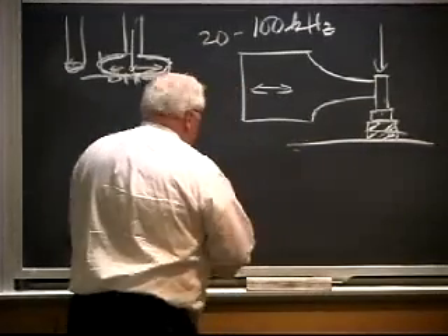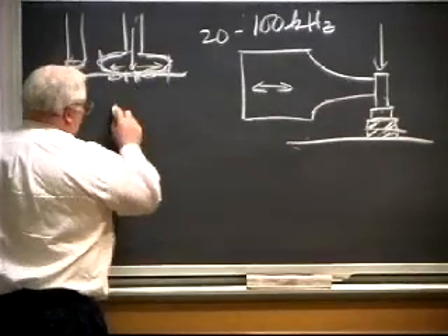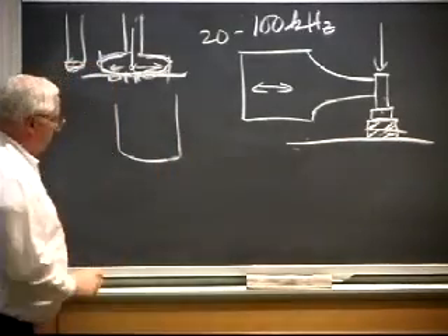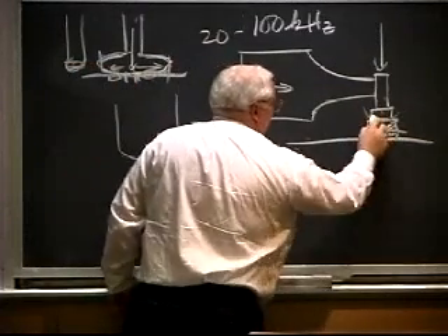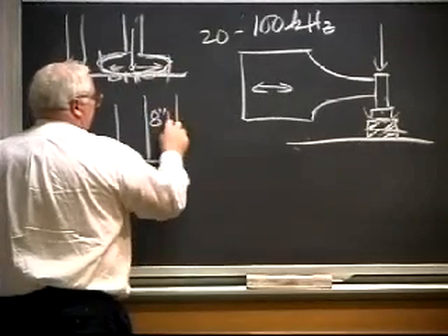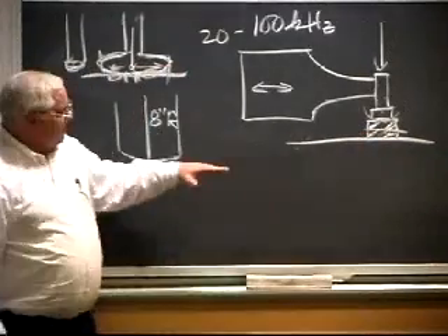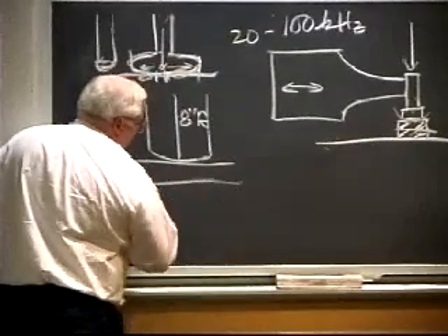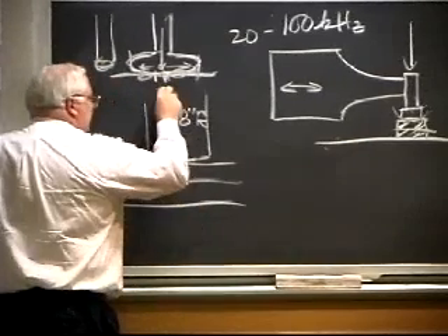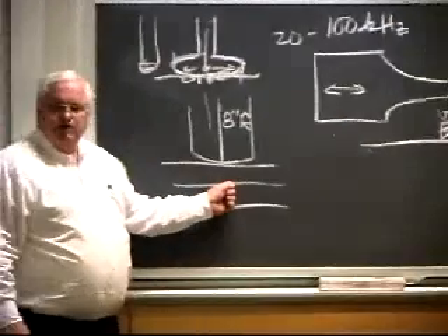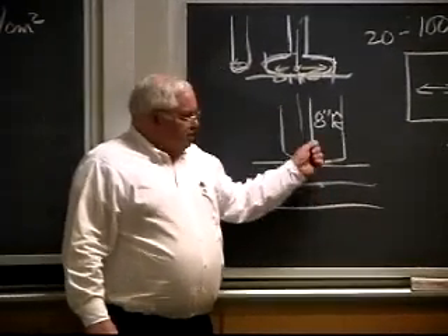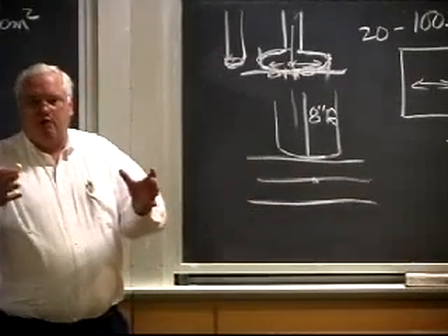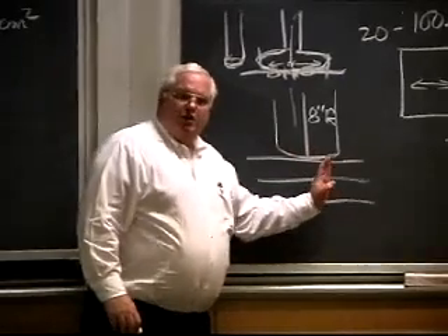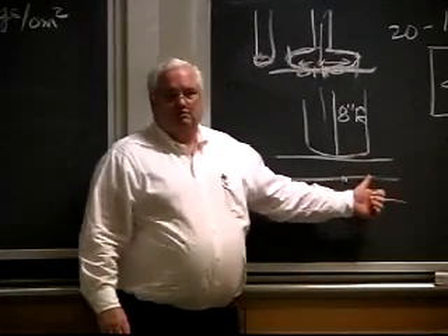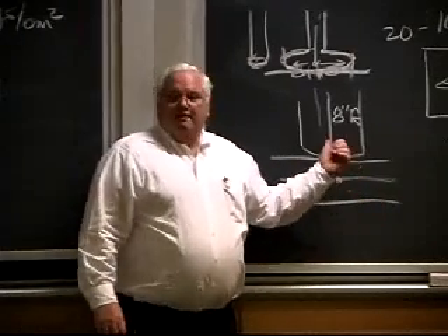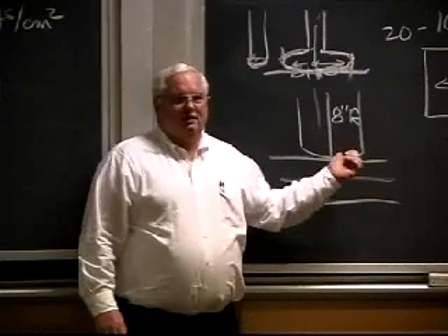Now, it turns out at Sandia National Labs once, they showed me that for some part of the nuclear warhead or whatever, they had this probe with like an 8-inch radius. The probe was probably smaller than that, but they put a very, very shallow radius on this, and then squeezed the plates together. They wanted to ultrasonically weld and increase the force over time, such that initially you had contact at one point and it was vibrating, and you kept on increasing the force, and so the contact area starts spreading out radially. They were essentially pushing a wave of oxide out, and they could get much stronger bonds. Maybe they only had 20 or 30% oxide contamination. Very expensive process to do this. Just to machine these things was not cheap.